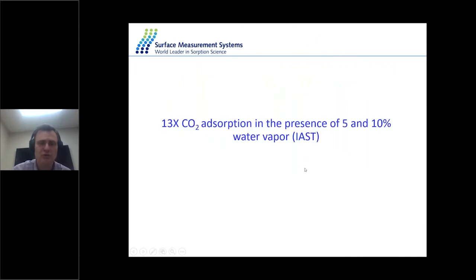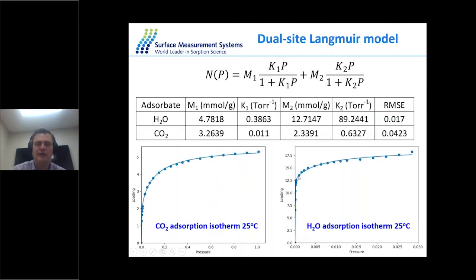Now I'm going to explain, I also briefly touched on co-adsorption. Basically we can do co-adsorption in dynamic and static mode. If you do co-adsorption in dynamic mode, we can do it with 5 or 10% of water. But what we really struggle with is that we only get one mass, and that mass data contributes both CO2 and H2O species. So in this case, we collect the pure CO2 adsorption isotherm at 25 on the left, and pure H2O adsorption here on the right. We have the curve, and we calculate the Langmuir constant.